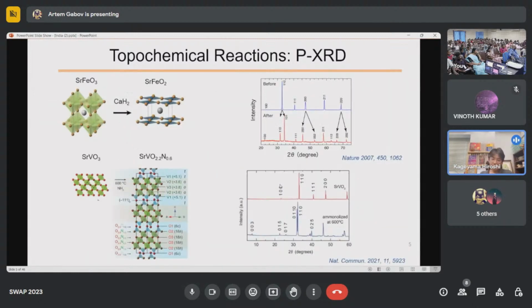And the same is true for the perovskite type oxide. In the first example, the top example, you see that the cubic lattice, the blue one, changes into the red one, where the red pattern can be indexed by the tetragonal, split peaks. Okay, so you can see the similarity between the diffraction patterns before and after reactions. The same thing is happening for this vanadium oxynitride material before and after the reaction. Some superstructure occurs, but basically the crystal structure looks the same. Okay, then you can maybe deduce the expected structures after the reactions.